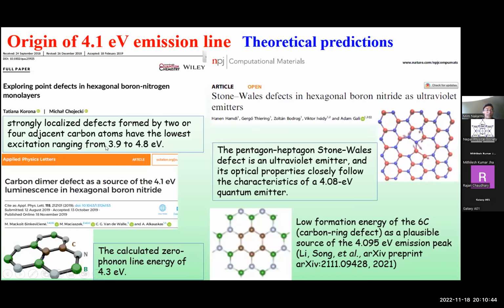Its energy could be from 3.9 to 4.8 eV. So that's one theoretical calculation. Another calculation from first principle says it could be because of two carbons sitting together, and that's called the carbon dimer, and that could be the origin of that 4.1 eV. Their calculation result is that its energy is 4.3 eV. And some people predicted it could be a different kind of structural combination.